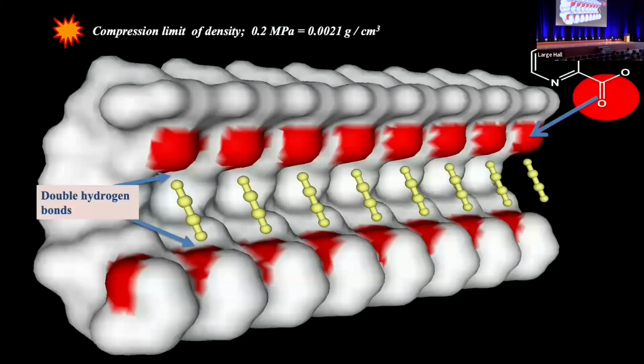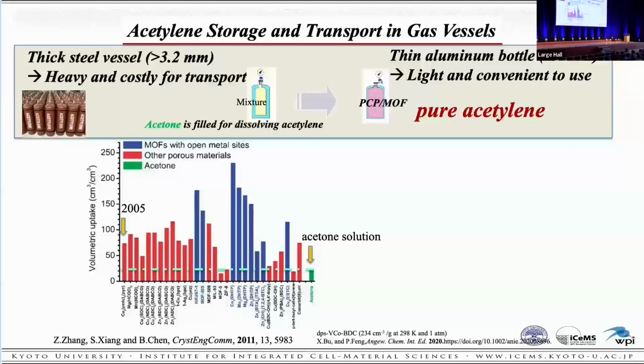The important point here is the double hydrogen bond between the acetylene and the oxygen on the surface of the pores. The density of acetylene in these pores is 200 times the explosive limit density, but it is still stably contained. Normally, pure acetylene is dissolved in acetone and pressed in a heavy cylinder, since it reacts explosively. If a cylinder filled with a MOF is used, pure acetylene can be stably stored.